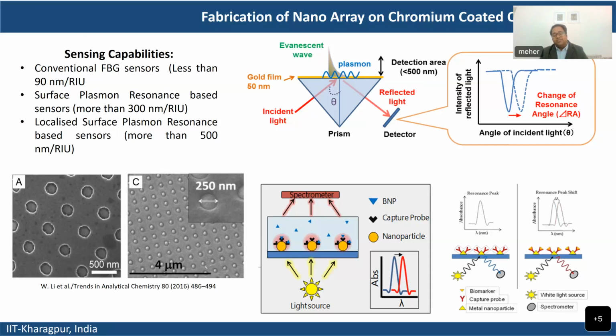So what to do if you want to sense some biological sample? There are some capture probes of that material, of that system, I should say. And if you embed those capture probes on your nanoparticles, then what will happen when these specific biological species come into contact with these capture probes? They will start sitting very selectively on the capture probes, and this will change the surface. This will change the refractive index in a localized manner, and this will change the surface plasmon resonance, and then you will have a shift in the peak. So this kind of sensor can be used in biological sensing also.